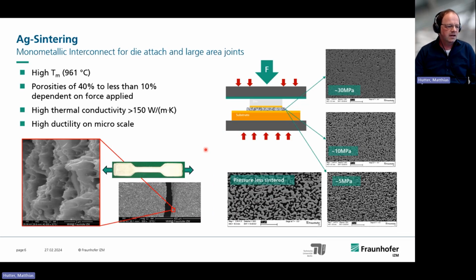The silver sintering is somewhere between the normal solder joints and the transient liquid phase bonded joints, because it's ductile. You can see that here on a micro scale. If you do a tensile test of such a material, you see that you have plastic deformation here on a micro scale. Of course, if you make a tensile test of a porous material, you macroscopically get a brittle fracture, but it's not the same as with ceramic materials.